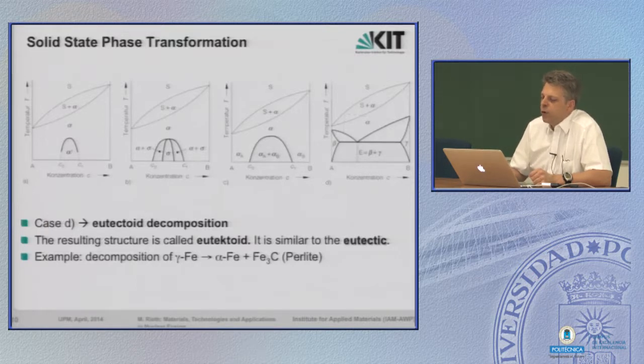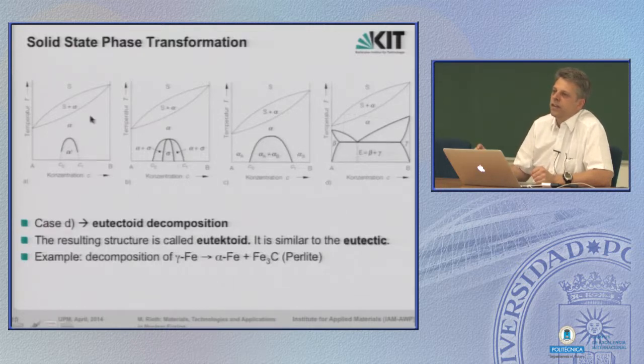There are also solid state phase transitions. You don't in each case have to start from the liquid. Sometimes, for example, if you have reached a solid crystal of alpha composition and you cool it further down, then further decomposition or formation of a second or a third phase appears. There are several cases. This one here is very prominent in chromium steel, where chromium iron mixed crystal decomposes into alpha prime and sigma phases. That's several other possible phases which could form here, depending on the chromium concentration.